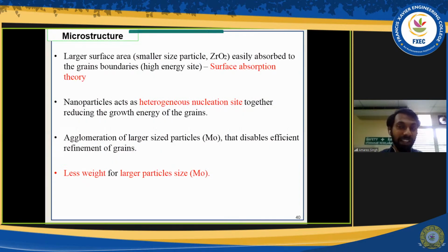This is what I have been explaining. When the nanoparticles are smaller in size, they are properly dispersed. But when they are larger in size, for example molybdenum, they should be given very much focus so that they are evenly distributed. Since we are manually distributing the nanoparticles, it's quite hard to have a proper distribution. So if you are using manual or mechanical stirring, you have to use smaller size nanoparticles. Unless we have an automated or an injection sort of nanoparticle machine, then we can use larger size particles and put the particles at a certain area to improve. Of course, it's cost.